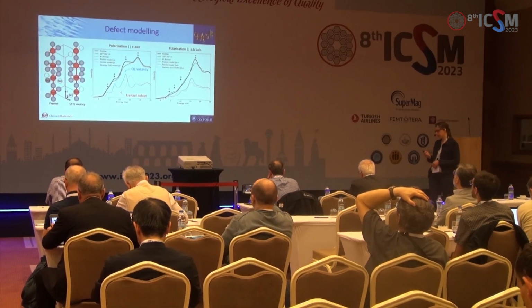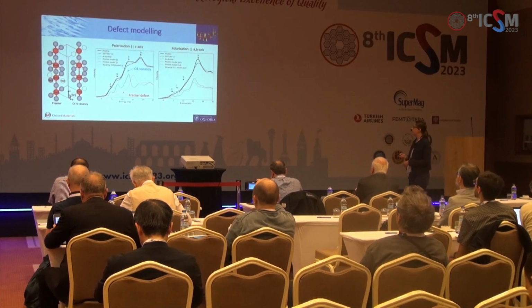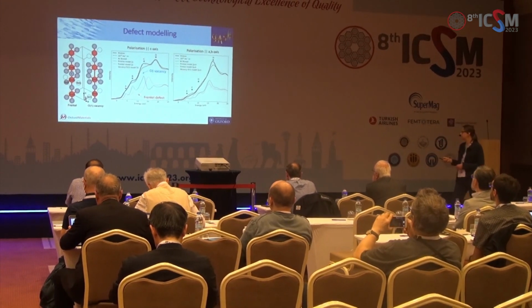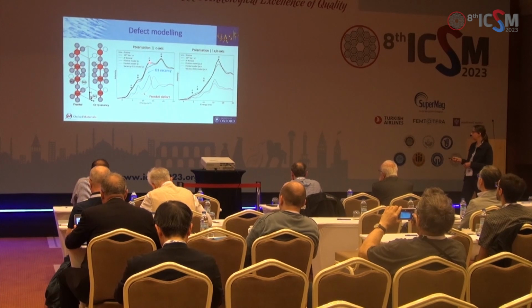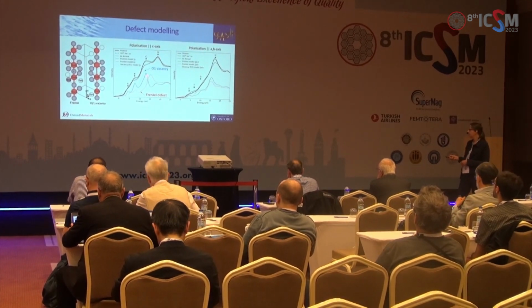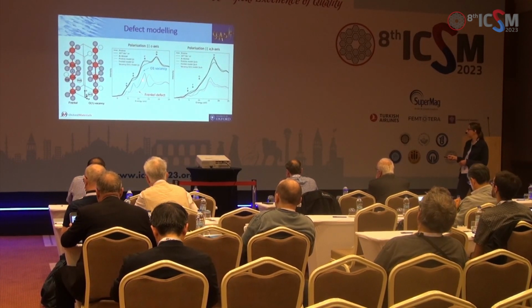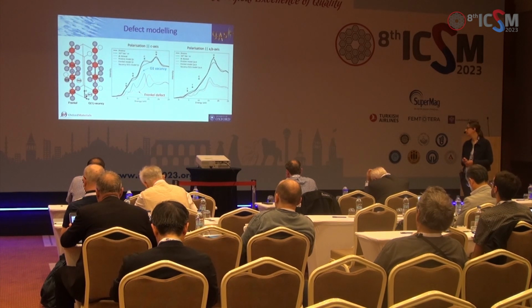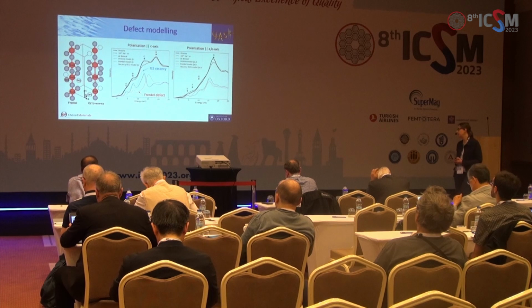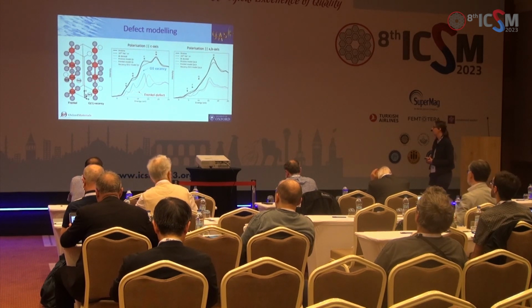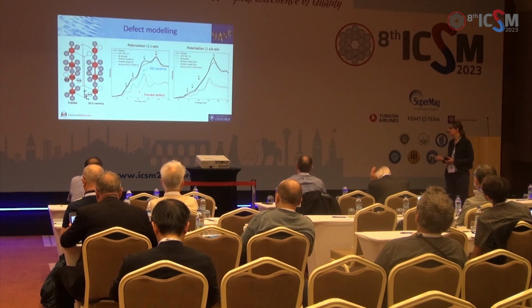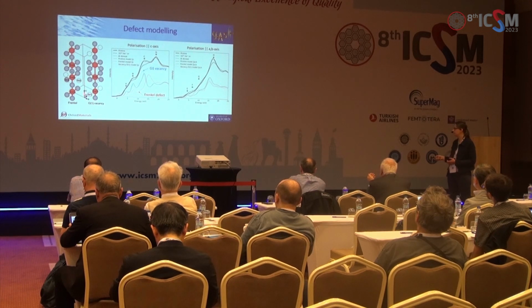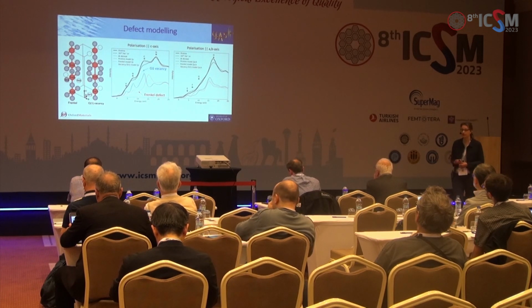And when we do the simulation, we can see what differences we'll get. So again, this is complicated. The black lines are the experimental data. The black line here is the modelled pristine structure. The red line is the Frenkel defect model, so what we would see if we had the Frenkel defects there. And the blue line there is the O1 vacancy, so that's pulling out the oxygen from this site, and that's what happens when we argon anneal. So we're using that as a comparison.